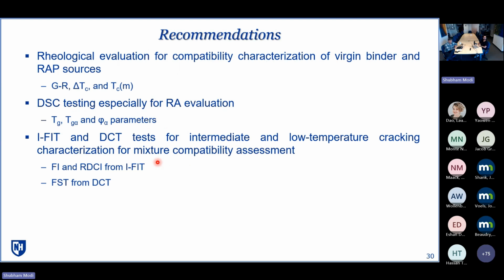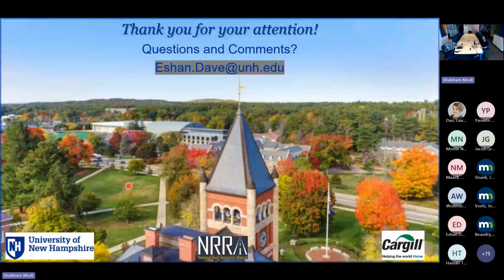And finally, the recommendation of this study was that rheological evaluation should be conducted to characterize the virgin binder and RAP sources, especially the Glover-Rowe, delta TC and TCM parameters. For higher confidence in the RA evaluation, DSC testing is recommended, and for that, TG, glass transition and related parameters. And for the mixture side, IFIT and DCT tests, with FI and RDCI from the IFIT test, and the FST parameter from the DCT test, are recommended. With this, I would like to thank you for your attention, and I'll be happy to answer questions.